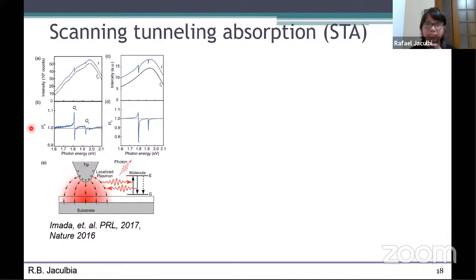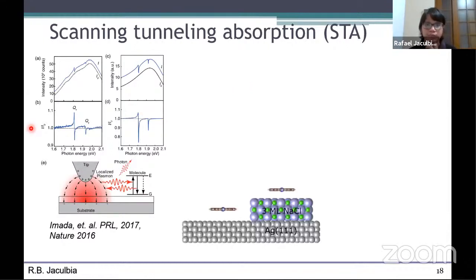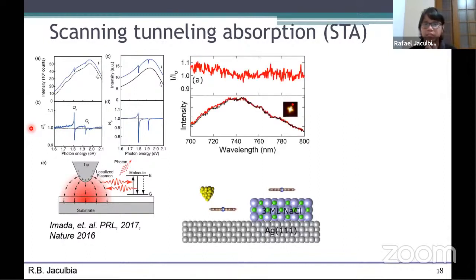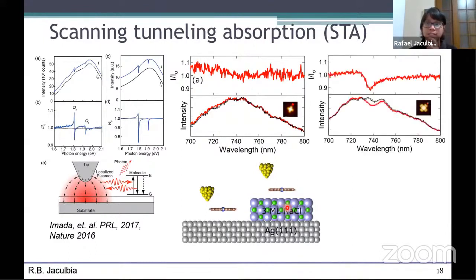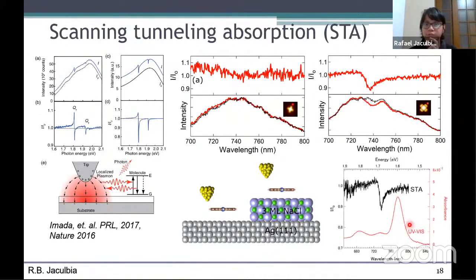And we applied this in order to confirm our results. We found that for the molecule on the metal, there were no signals in the vicinity of the excitation light we used. And then when we placed the molecule on the sodium chloride, we could easily detect this dip, which corresponds to the absorption of the molecule, as also confirmed by room temperature UV-Vis measurements in solution form of this molecule. So now we know the absorption spectrum of the molecule, we can perform resonance Raman spectroscopy.